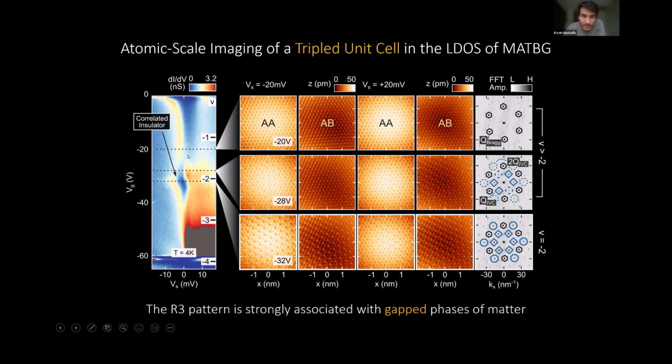As we sweep the chemical potential into the gap phase, we see continuously that the √3 pattern onsets at all places in the Moiré superlattice across every region, and concomitant with the appearance of a set of inner peaks, which we call q_IVC, and some higher replica peaks, 2q_IVC, because of the dominance of the √3 pattern.